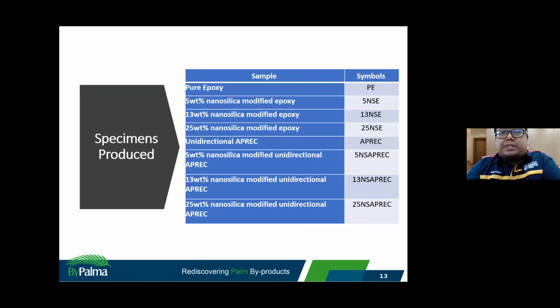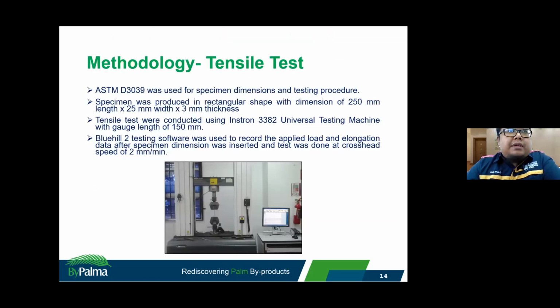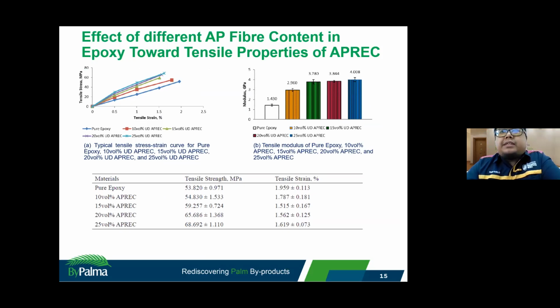We have pure epoxy, nano-modified epoxy, and also unidirectional APREC and nano-modified unidirectional APREC. On the tensile test, we are using an Instron 3382 universal testing machine with a gauge length of 150 millimeters, following ASTM D3039. The crosshead speed is around 2 millimeters per minute. So this is the result.